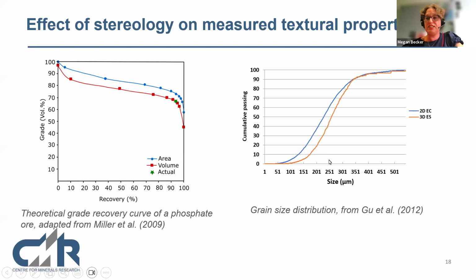From a grain size distribution, the 2D shown in blue tends to estimate that it's slightly finer. And so we know this error exists. What do we do about it? We sort of just work around it. And I think that if the mineralogy says a grinding target must be this number, there's always some sort of window that's provided on that estimate to account for the stereological error.